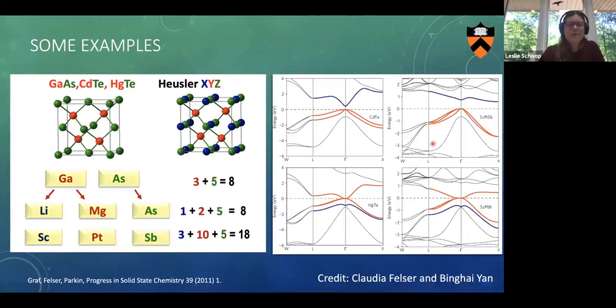Well, for example, we can think about semiconductors by just looking at electron counts. So you might know that gallium arsenide is a very famous semiconductor. And if I count the electrons, I get 3+5, which is eight electrons. And then I can keep playing this game and go to ternary compounds. And if I count to eight, I will still get a semiconductor. Or if I include d elements from the d block, I count to 18, I will still get a semiconductor. So you see here, scandium platinum antimony, which is not intuitively a semiconductor, but because of the electron count, if you look at the calculated band structure, you see that it has a band gap as a semiconductor.